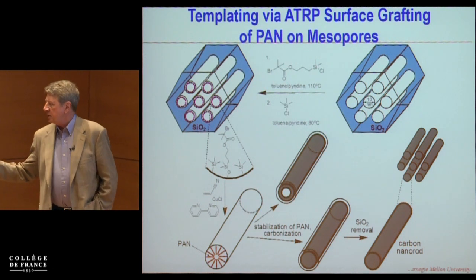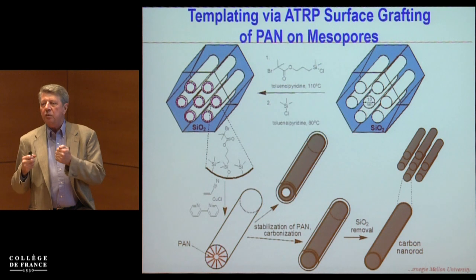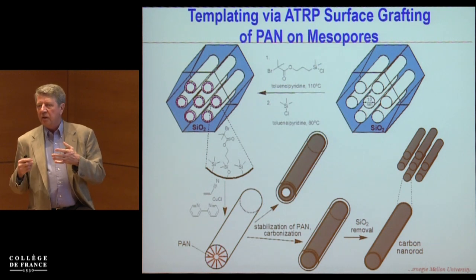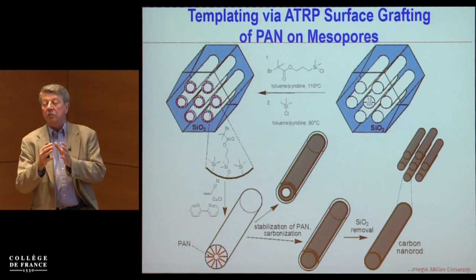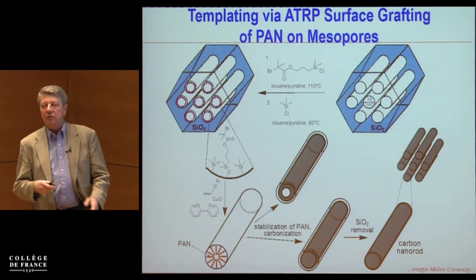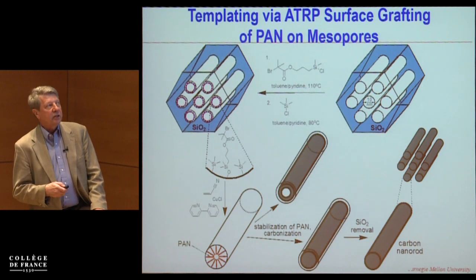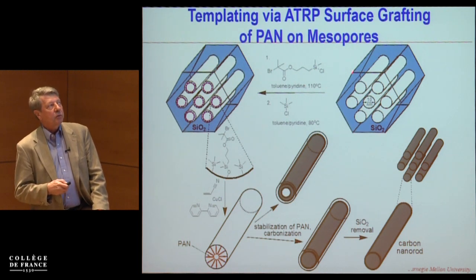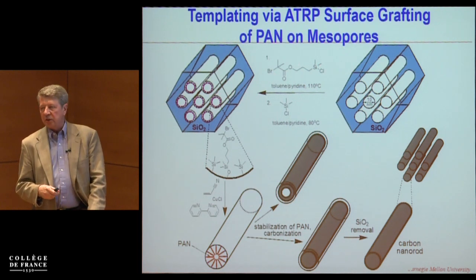Now, something which we discussed with Professor Sanchez several years ago is whether you can efficiently grow polymers from inorganic surfaces in a limited or confinement regime. So if one starts from mesoporous silica, these are SBA 15 with 10 nanometer diameter holes or cylindrical structure, we can put in, using chlorosilane chemistry, these bromo initiators, and then start growing polymer chains.